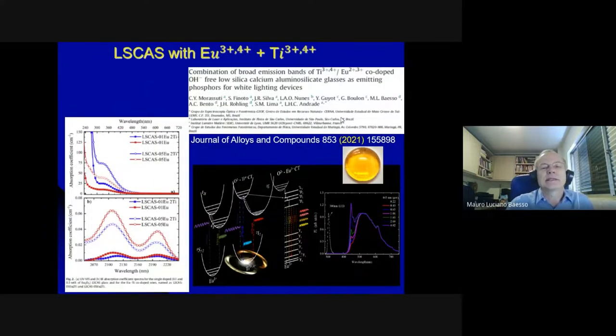And then after that, this paper is from this year, 2021. We had the titanium paper before. We published a Physical Review Letters paper because only in our glass under vacuum atmosphere are we able to obtain titanium 3+. Usually in oxide glass, if you melt it in air atmosphere, you get titanium 4, and the glass is transparent. But to get titanium 3, you need to change the condition of your melting.